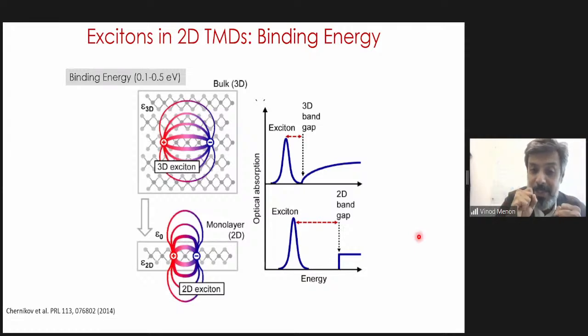electron and the hole that are in these materials, the flux lines between them, the screening gets modified. The screening is very different. So there is very weak screening outside, and so the screening only happens in the 2D limit. And the result of this is these electron and holes are very tightly bound, and hence they have a very large binding energy. So they have a binding energy on the order of 0.1 to 0.5 eV.